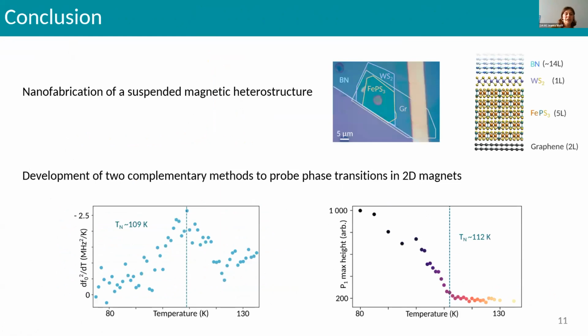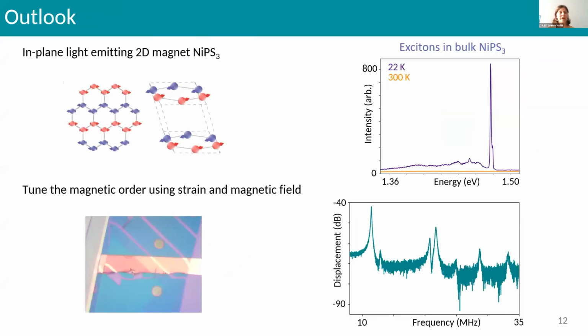To sum up, we fabricated a sophisticated suspended magnetic heterostructure, and we developed two complementary methods to probe the phase transition in the magnets. For the future, we are also interested in another 2D magnet, which is NiPS3, which has an in-plane magnetic order but also possesses light emission, excitons, in these materials, as you can see from these first results. The next project is to tune the magnetic order and also the photoluminescence in these materials with a suspended sample that, as you can see, is already vibrating.